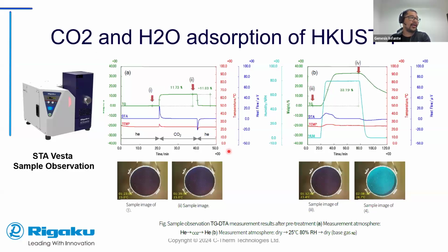On the left, it's more about controlling the gas atmosphere that we are introducing to the system. You can see here that initially, no mass change, no change in the thermal events, no temperature change, and that's mostly because it's just helium being inputted to the system. It turns out helium is not coordinating within the MOF itself, so there's no mass gain. And then once that helium is swapped to carbon dioxide, you can see that there's a drastic immediate response where you have an exothermic event and an increase in temperature and increase in mass right away, at about 11% in this case. And then it saturates. And then, when you remove the CO2, you can see that it releases very quickly once the helium is reintroduced. So yeah, that's pretty much it for CO2 and thermal analysis techniques.